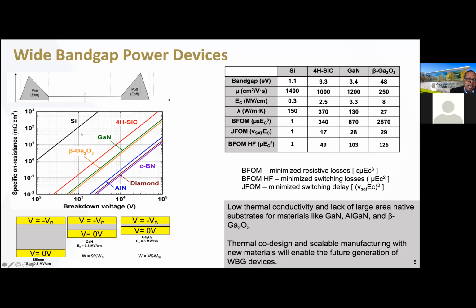If you look at this graph, you can see that for a given breakdown voltage, if I'm here with silicon and I move to a wider bandgap material, then my theoretical specific on-state resistance would be much lower. And if I move up in bandgap again, it drops again. So this breakdown voltage versus specific on-state resistance allows you to design devices, shown here, that if I go from silicon and go up in the critical field and breakdown voltage, I can make a device out of gallium nitride, theoretically, that would be 9% of the thickness of silicon. And if I go to gallium oxide, now it's only 4%.